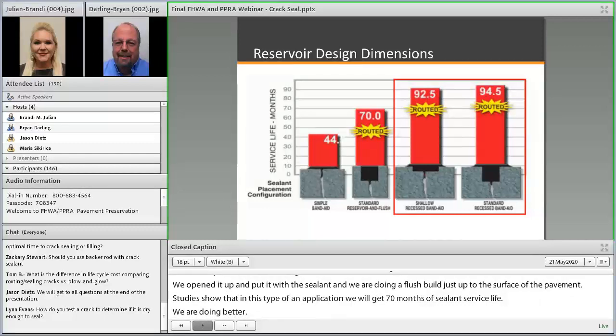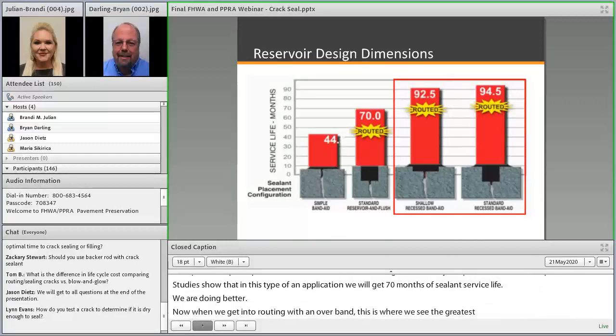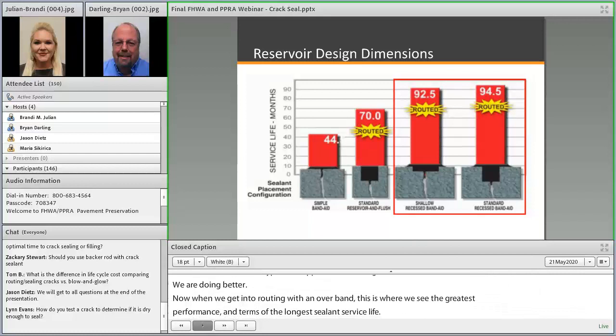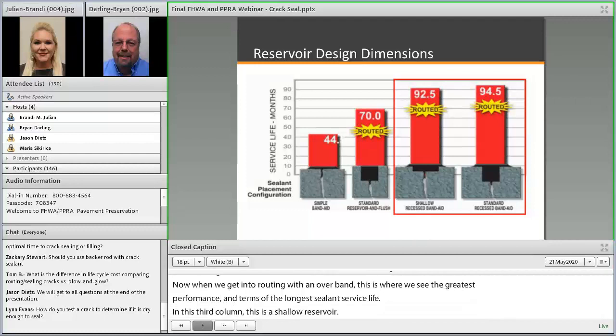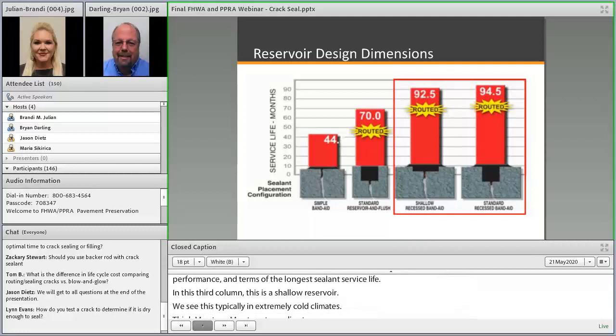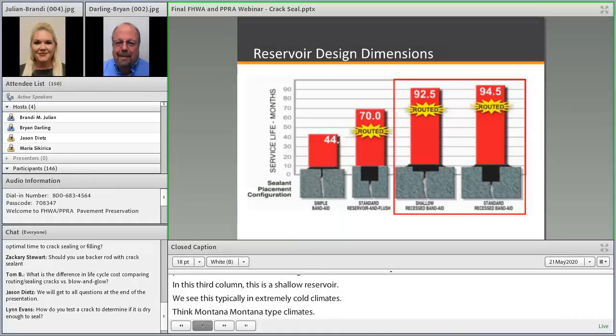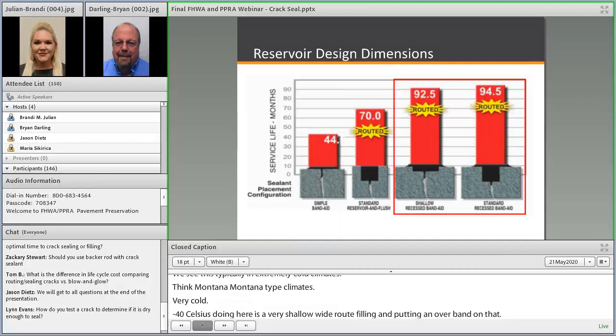Now when we get into routing with an overband, this is where we see the greatest performance in terms of the longest sealant service life. So in this third column, this is a shallow reservoir. We see this typically in extremely cold climates. So think Montana type climate, very, very cold, minus 40 C. What we're doing here is doing a very shallow, wide route, filling and putting an overband on that. And we're seeing 92.5 months of sealant service life in this type of an application.